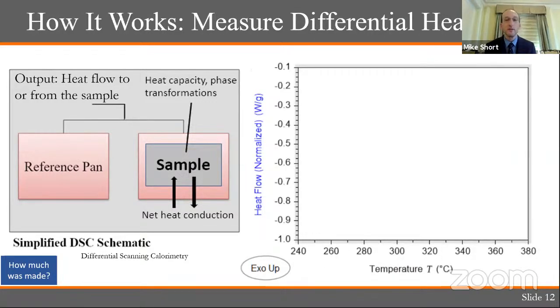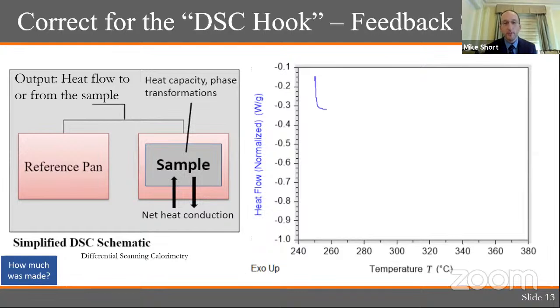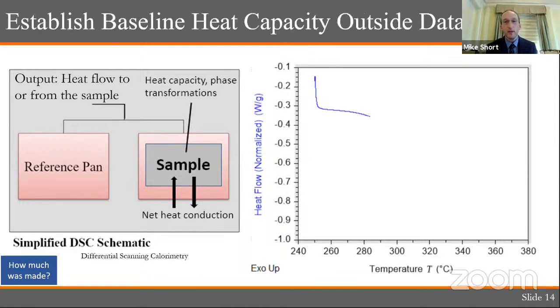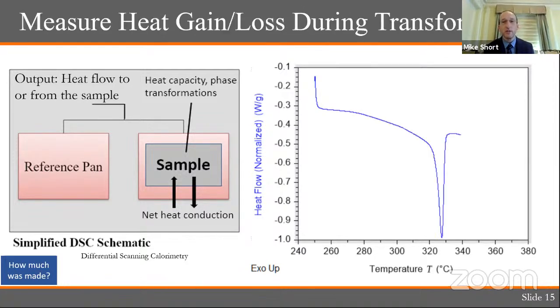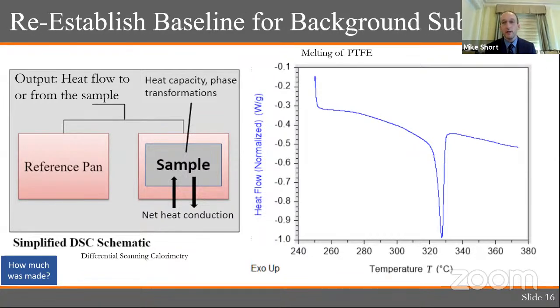I want to show you what these signals look like so that you can see whether or not we can actually tell these differences. When you start off by measuring, let's say heating up or cooling down, you'll go through an initial transient where the instrument is sort of getting to know your sample, so to speak. You keep heating and establish a physical baseline. And when you heat through some phase transformation, you're going to see a large energy absorption or release peak. This is going to be the focal point of our study because radiation will change the shape and size of this peak.